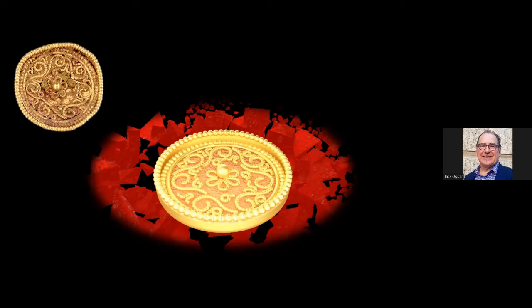And then at about 890 degrees centigrade, it both alloys with and diffuses into the gold. So it creates a solder actually at the point of contact. It's an extraordinary technique. Now, some ancient goldsmith wasn't sitting in the bath trying to work out how they might be able to do this, coming up with the idea of copper salts and reduction. No, it's a byproduct of something else, undoubtedly. The same coppery mixtures and gold were used for painting walls and putting on eye makeup and for glazing stones. So there are various other ways. It could have been an accident to start with, but very early on, probably 3000 BC, they discovered this technique. And it was certainly being used before 2000 BC, what we call copper salt soldering.